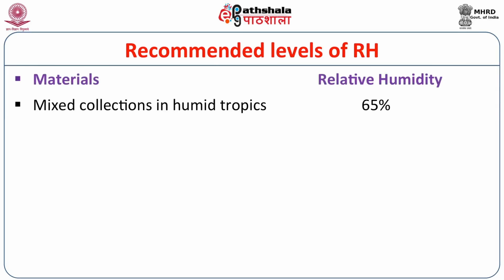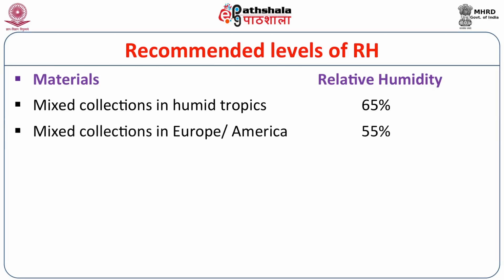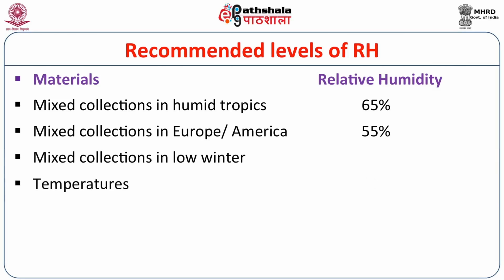Here we should mention the recommended level of relative humidity for different types of objects. For a mixed collection in a humid tropical climate it should be 65%. A mixed collection in Europe or America should be 55%.